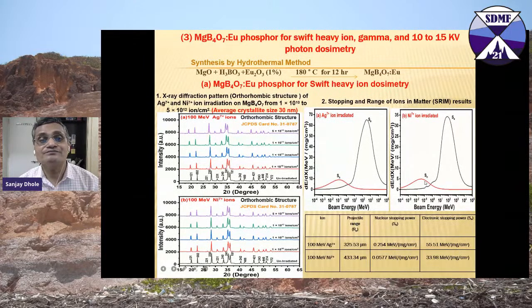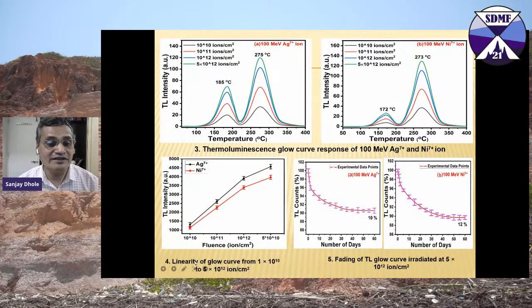And this is the last one. We could also perform experiment for ion dosimetry. This is all for the magnesium borate doped with europium for a swift heavy ion, gamma and photons. I will just let you know the response, linearity, glow curve response for 10 power 10 to 10 power 12 ions per centimeter square for the silver ion having charge state 7 plus and nickel ion having charge state 7 plus. See, the linearity is quite maintained, but the fading is 10%, and for 100 MeV nickel is 12%. This is not that good one.